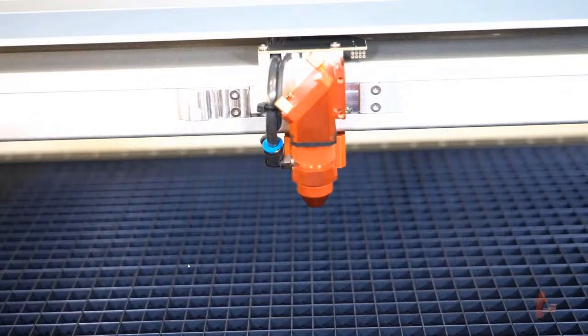Wide mouth cone is also ideal if you're doing a lot of engraving or thin cutting, like your engravable plastics, your Trolase plastics, your Romark plastics, IPA plastics. This is going to keep them from frosting as much. It's going to keep the flame down, but when you use the small mouth cone with your air assist, it can actually cause your plastic to produce more debris and residue. And that debris and residue can be hard to clean off. I actually have laser hacks online on how to clean those plastics mainly because of that. If you use the wide mouth cone, it reduces that because it keeps the flare from damaging the optic, but it dissipates that pressure. And so you don't get as much debris and residue when you use the correct cone with the application.